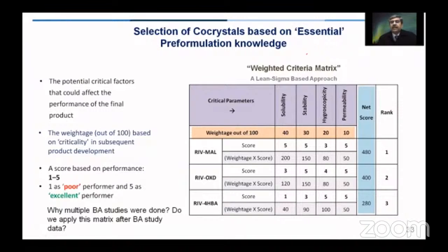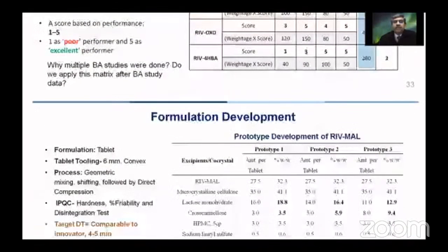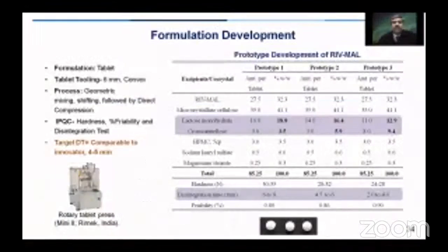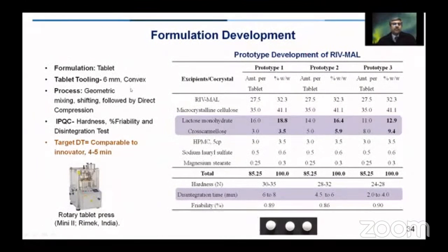Based on this, we can conclude that the malonic acid co-crystal was the best one for carrying out the further development into a solid dosage form. And we then developed a prototype formulation for the co-crystal with malonic acid. We developed prototypes using the excipients that are shown here. The formulation was a tablet.